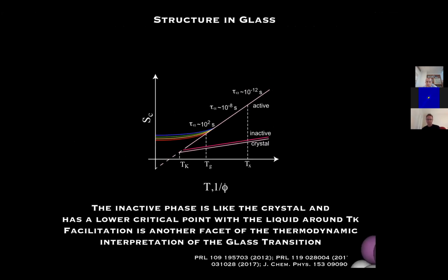So what does this all mean? What it means is that these two very different interpretations of the glass transition, the dynamic facilitation interpretation and the thermodynamic picture, are actually different facets of the same thing, at least for the systems we're looking at here. And so in other words, we can bring these two interpretations of the glass transition together and say that the dynamic facilitation is like a facet of the thermodynamic picture, and essentially they are different ways of looking at the same thing. So that's what I wanted to tell you. Well, that was the story.